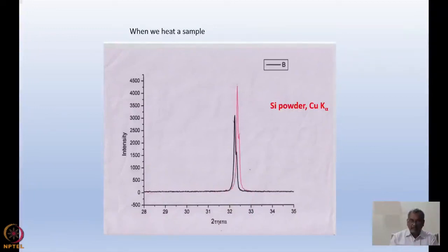Actually, in our diffraction experiment, this is also one parameter which is fitted to find out the thermal parameter, where you can say that the thermal parameter, or the extension, or the extent to which the atom is vibrating, is given by the Debye-Waller factor and also fitted as a parameter.